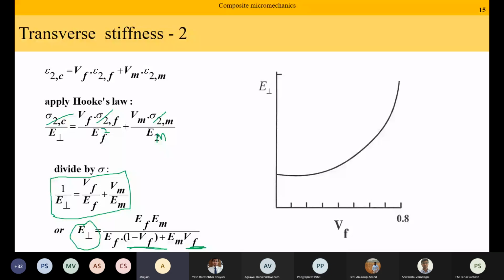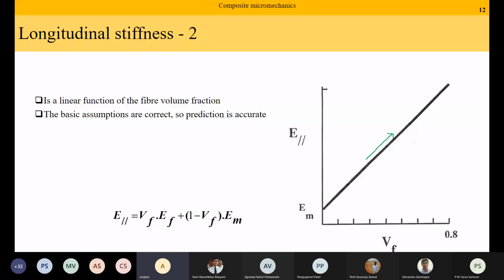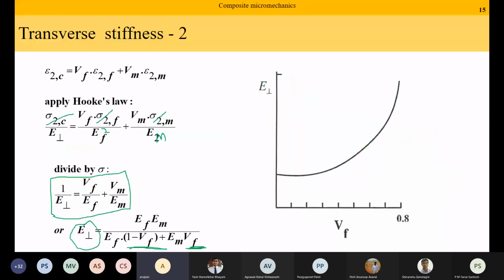Now, look at this plot carefully and tell me, what can you say about the benefit of adding more fibers? For longitudinal stiffness, we had this relationship where as I was increasing fibers in a linear manner, the modulus was increasing. Now, look at this plot and tell me, what can you conclude about the modulus increase as I increase the fiber? With very small change in the volume fraction of fiber, we are getting a very good increase in the stiffness. But in fact, this is only at this end, higher concentration. Correct. At the lower ends, by increasing fiber, you are getting very little benefit in the modulus increase of composite.